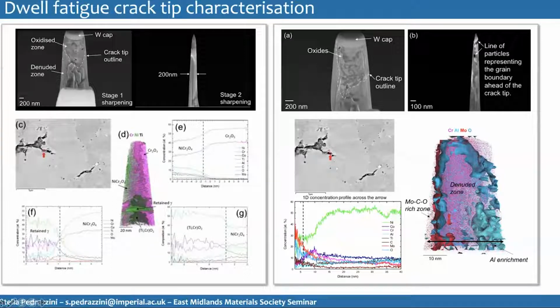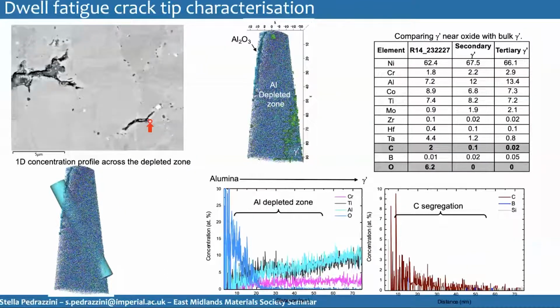And looking at a concentration profile going this way, we can see that the chromium and the cobalt are being rejected into the alloy. And at the grain boundary, what we have is some molybdenum, some oxygen, and some carbon, and a nickel depletion there as well. So now I'm building a picture of what this all means at the crack tip.